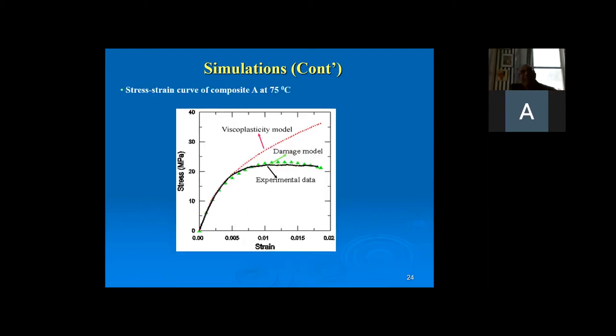And then again, for composite A, at 75 degrees Celsius, of course, polymer has much smaller elastic modulus. Keep in mind that the glass transition temperature for this polymer is 90 degrees, and this polymer actually melts at 100 degrees Celsius. It is like a liquid at 100 degrees Celsius. So ultimate stress goes down significantly. But again, if you don't include the unified mechanics theory thermodynamics state index, you get this model stress strain response. And then once you use the thermodynamic state index, unified mechanics theory formulation, you get the experimental data.